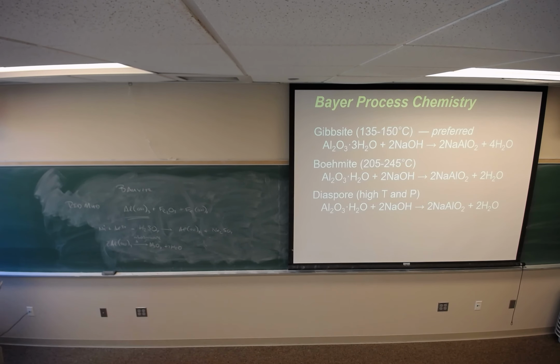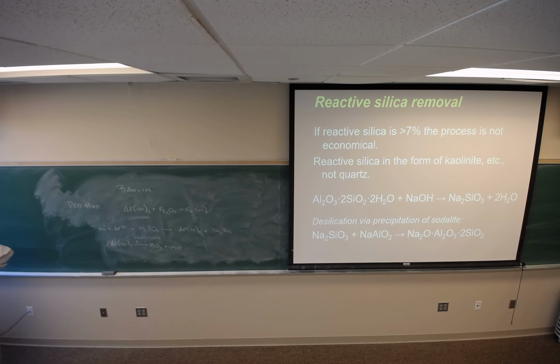We prefer gibbsite, 135 to 150 degrees C, so you know it's under pressure. Plus it's a high concentration solution, which drives up the boiling point. Okay, there's your reaction. Boehmite, you have to go above 200 degrees C, that becomes expensive. And diaspore, you have to add pressure to it. This is your reactive silica that I talked about. If the reactive silica is greater than 7%, the process is not economical. That fits into the grades of the bauxite. So if they're grading the bauxite and they come back and say there's too much clay, then it can't be a metallurgical grade, and they have specifications for those grades. Okay.